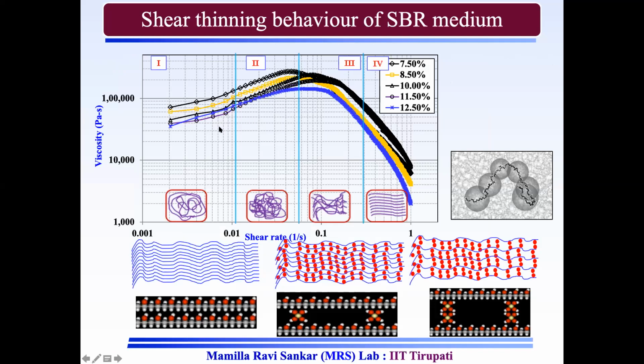If you see here, the most important thing from this particular curve is, as you increase the shear rate, the viscosity in the first region and second region is increasing, and in the third region it is decreasing. Okay, so why is it decreasing? As you can see here, you have seen the rheometer plate. If I am using a shear rate, that means my top plate is rotating. Low shear rate means it is rotating at low speeds, whereas high shear rate means it is rotating at faster rates.